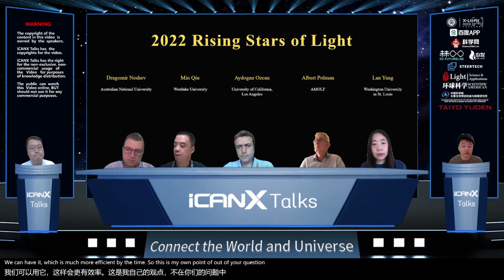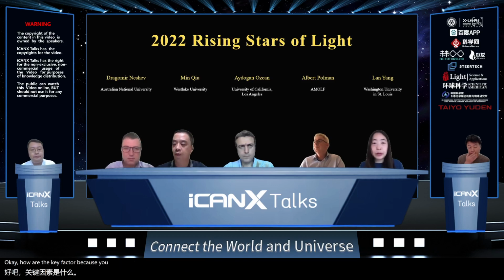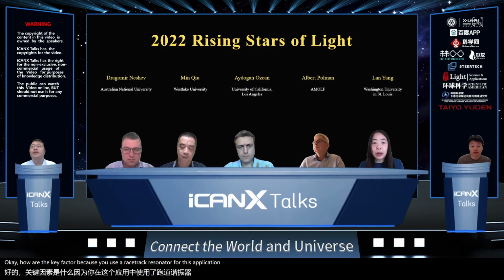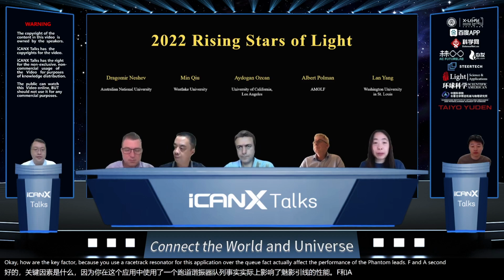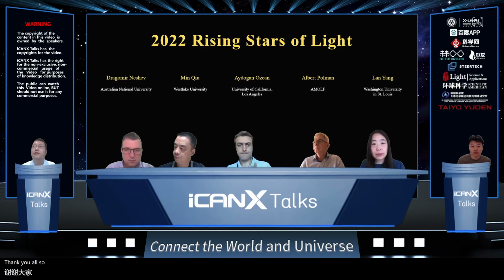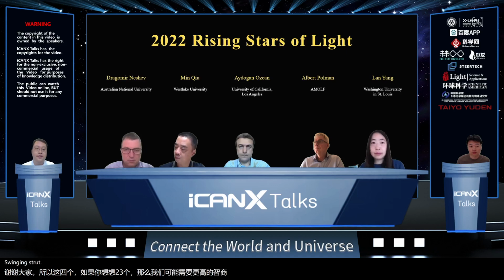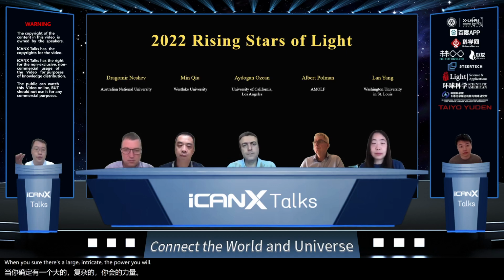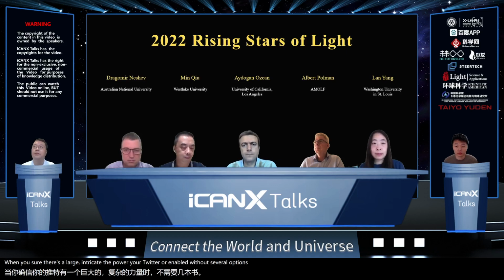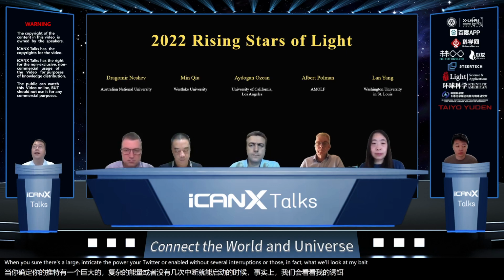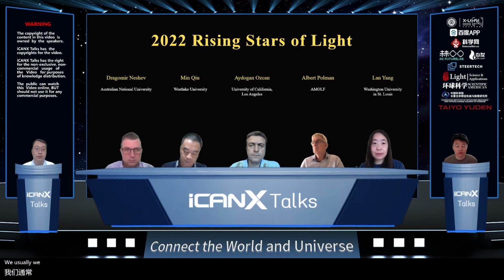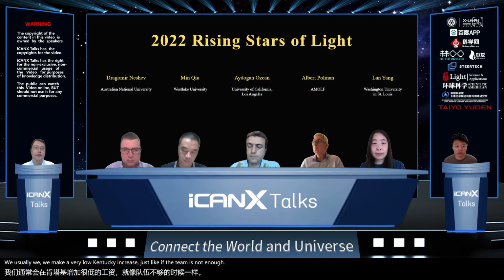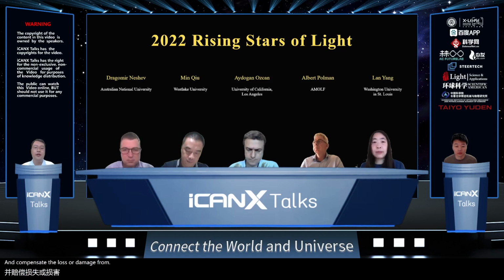Yeah. Okay, how about the Q factor? Because you use a racetrack resonator for this application, how will the Q factor actually affect the performance of the femtosecond pulse? Thank you. If you think about Chi3, we probably need a much higher Q to ensure there's a large intracavity power to enable the saturable absorption effects. But for lithium niobate, we usually make a very low Q cavity, because if the gain is large enough, it can compensate the loss. So then we can already go beyond threshold.